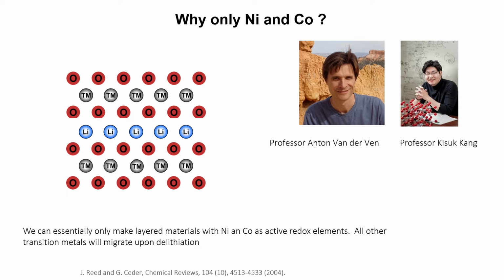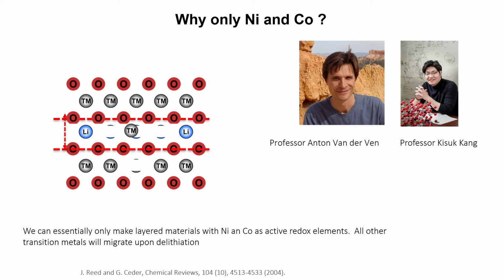So here's a sort of cartoon of a layered oxide. When you pull lithium out, this is the skill of my animation level. There's a lot of vacancies there, and transition metals tend to migrate into those vacancies. And they need a single hop, right? Only a single hop. You're going to operate these batteries for 10 years, and you have to prevent a single hop. Because what happens when the transition metal migrates, the layers around it contract. And I'm going to show you that when the layers contract, lithium diffusivity gets completely killed. And so the only metals, as I'll show you, that don't do this is nickel and cobalt.